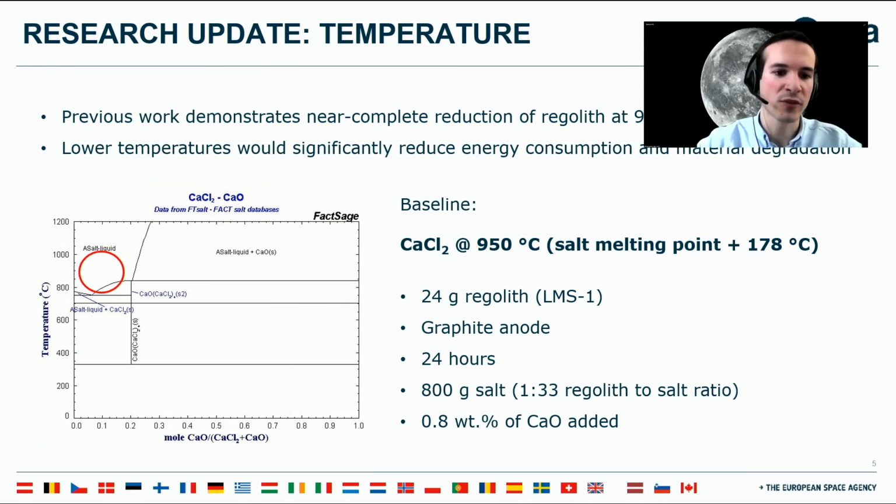Regarding the calcium oxide content, this is also key to the process. So here we add 0.8 weight%. We already have 0.2 in the salt. So we have around 1 weight% of calcium oxide in the process.